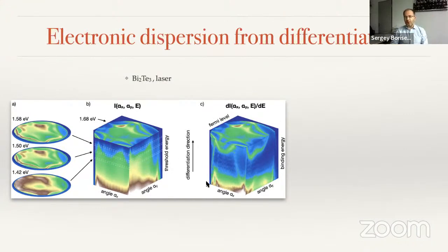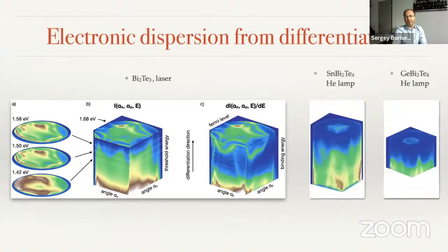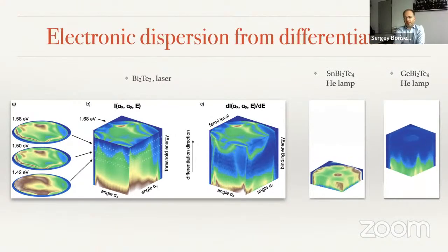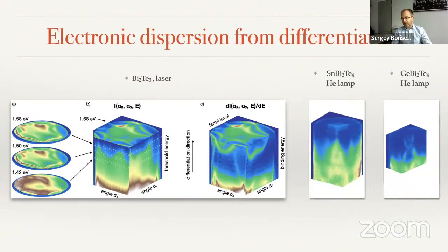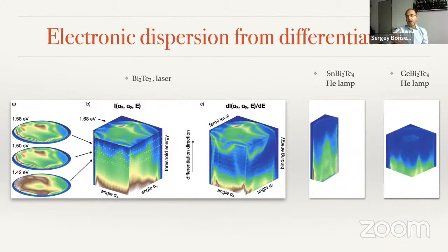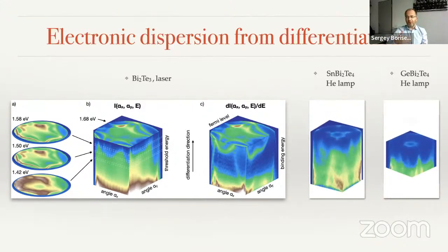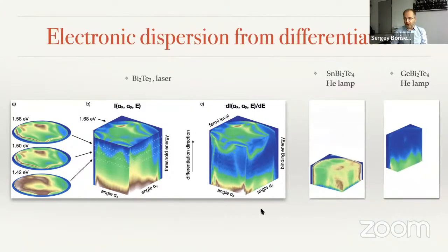Then another step which you need to do is to differentiate the data set along this direction. And then you get the dispersion of electrons as you used to have it in a conventional analysis. Alternatively, you can record the data in a lock-in mode, and then like in tunneling spectra, you could see directly the derivative. In this way, you can record, of course, a lot of data. You could see the full k-omega space within a pretty limited amount of time. The difference, again, is that you have the momentum distribution and not momentum energy distribution as in a conventional analyzer.